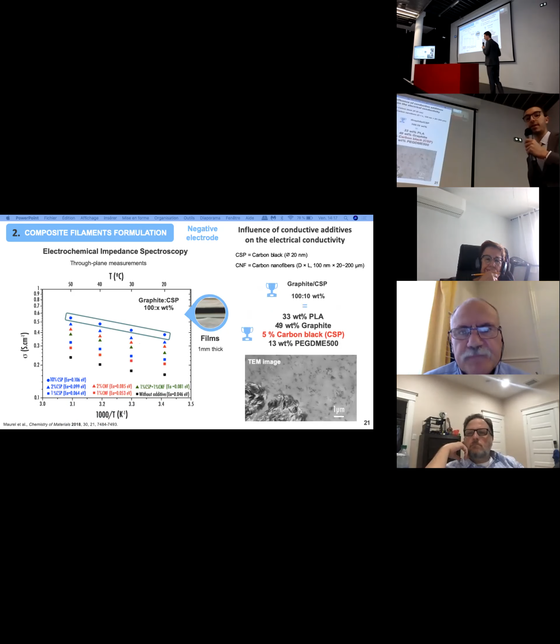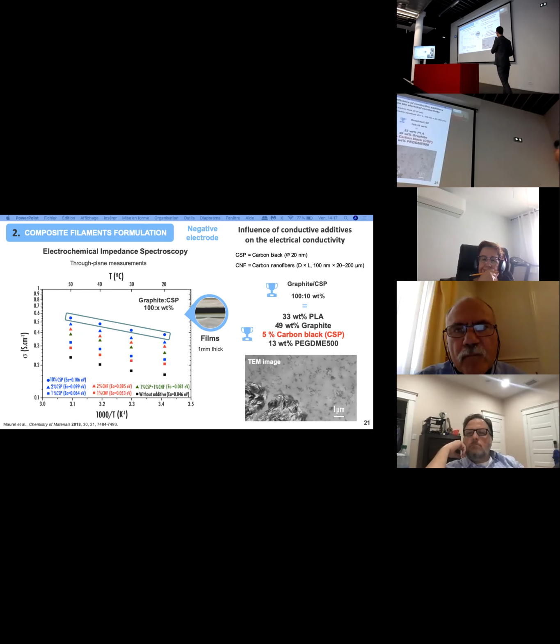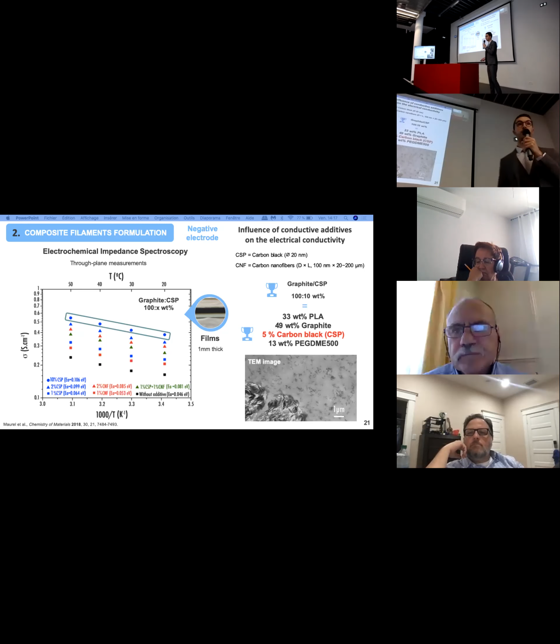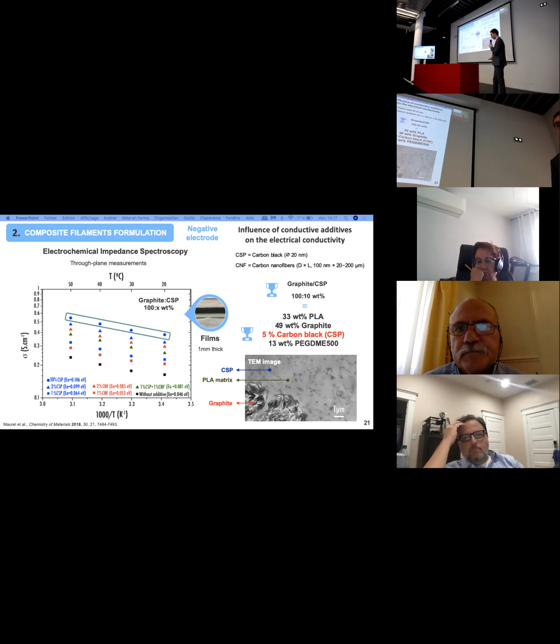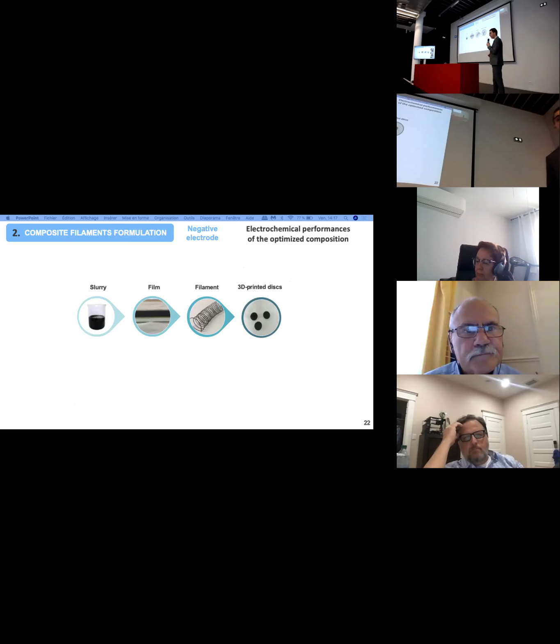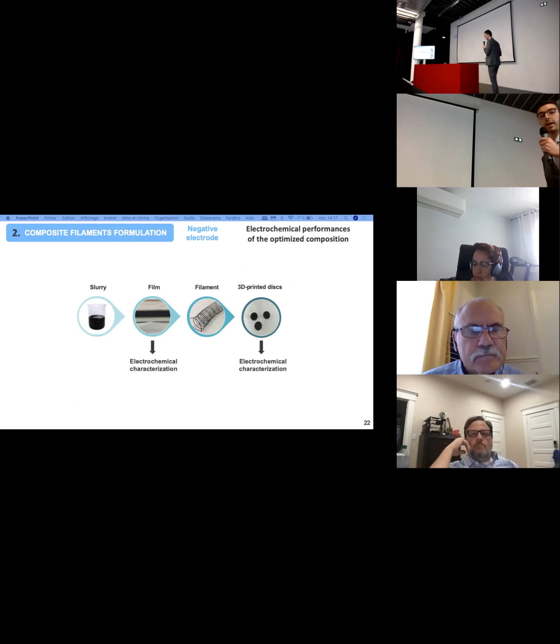Here is the optimized amount, the optimized ratio of the filament. So 33% of PLA, 49% of graphite, 5% of carbon black here, and 13% of PEG-DME 500. If you take a look at the TEM image, you can clearly see that the carbon black is really well distributed within the PLA matrix here. Again, as I previously mentioned a little bit, we pursued with electrochemical characterization on both films and 3D printed discs.